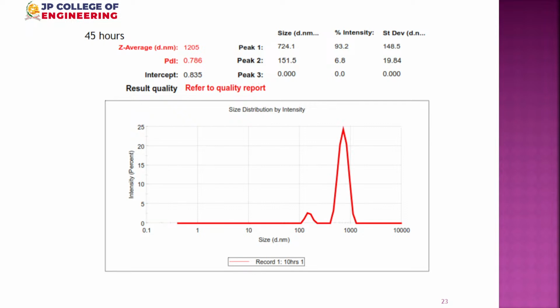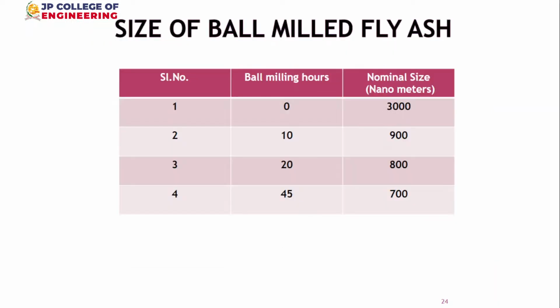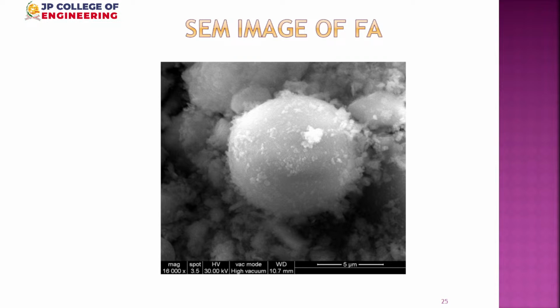Next slide, please. So for our studies, we have selected the serial numbers 2, 3, 4, called 900, 800, and 700 nanometer size particles, which we have used for our further study. Next slide, please. Using this, we have prepared our composites. This analysis showed even some amount of larger particles, 5 micron, but you can see in the background there are no small particles. They are submicron particles. So by grading, we remove the large size and use only the small size particles for our preparation of the composites.